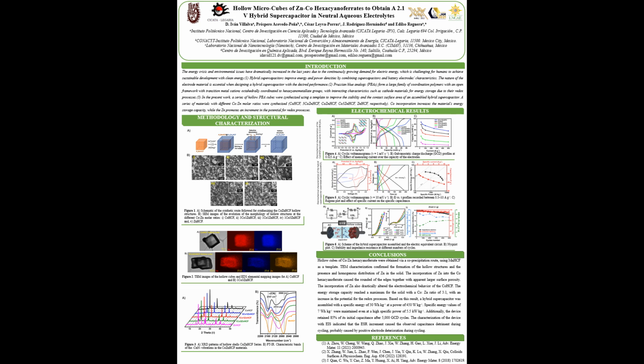The capacitance values are plotted in figure 6c, blue line, indicating that the device storage capacity has a stable trend with a slight decrease during cycling, as measured from galvanostatic charge-discharge. In the same way, another relevant parameter is the series resistance of the device, green line, equivalent series resistance. The continuous increment of the equivalent series resistance indicates that capacitance loss during cycling may be related to the electrolyte resistance increment, probably caused by the insertion-extraction process of the potassium ions in the positive electrode.